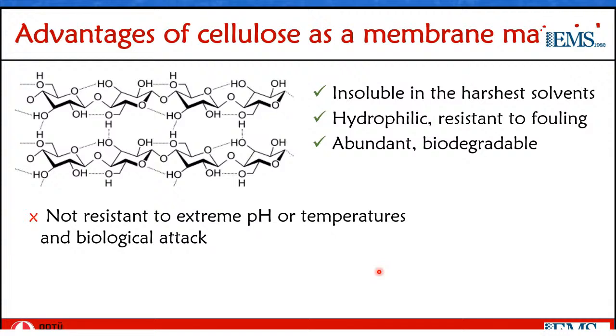Considering the challenges and needs in membrane processes, cellulose has a number of advantages. To start with, it's insoluble in many organic solvents, including the harshest polar aprotic solvents such as NMP, N-methylpyrrolidone, DMF, dimethylformamide, and so on. This, of course, at first brings an advantage in making the membrane, because typically you need to dissolve your polymer in something to make it into a membrane. But then once the membrane is there, it's a great advantage because you can simply use this membrane in any of these solvents.